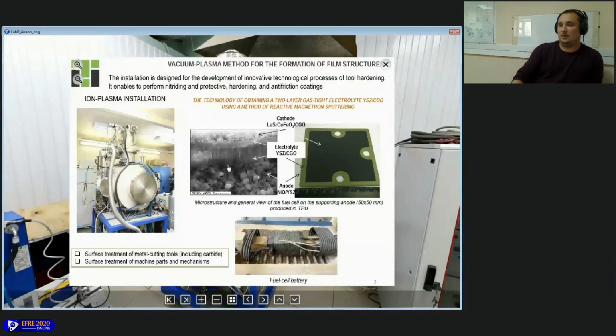We use a thin electrolyte based on yttrium-stabilized zirconia. We also have a supported anode, which we use as a support, and then deposit the solid electrolyte on it. We have also now started working with a cathode, which is quite complex. The thickness of the electrolyte is relatively small, less than 5 microns. Compared with the standard techniques, it's like 100 microns and so on. So here is one of the benefits of magnetron sputtering, because we can produce very dense and high quality films with a very low thickness.